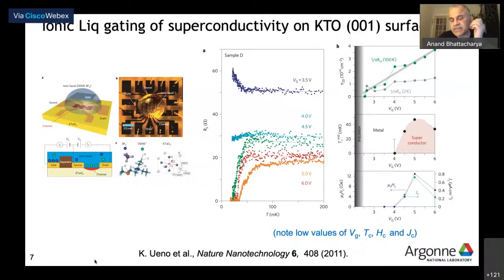There were several very interesting things about this work. They saw a dome in TC, but they also saw very, very small, very low critical currents and very low critical magnetic fields. All right. And for those of you who worked with ionic liquids, this was still sort of early in the day when ionic liquids were being used widely, now of course, to do all kinds of gating. Now it's well known that at these voltages, like 6 volts that you apply, you get electrochemistry at the surface. So you get ion exchange, you get oxygen vacancies formed and all kinds of interesting things happen. But nonetheless, it was very exciting when this happened.